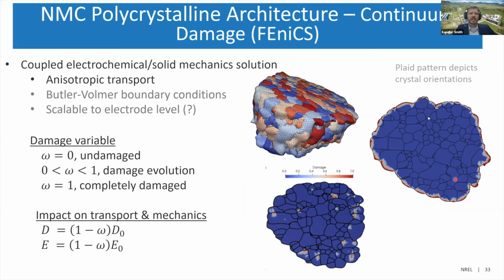Okay, in the FEniCS model, what we've done is to develop a continuum damage model. And so similar to, kind of borrowing from, the lattice spring model, it tracks a damage variable, which is 0 when undamaged, and then can transition to a completely damaged state. In this model, we've got anisotropic transport. We're working to include all of the realistic electrochemistry, such as the Butler-Volmer boundary conditions.